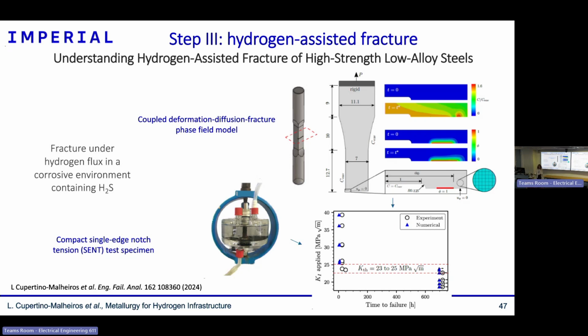Yeah. Sure. Some questions online. Someone asked, how much time does it take for hydrogen desorption to begin in BCC steels after ex-situ hydrogen charging? It depends on your geometry. Basically, you can estimate that. Just take the diffusion coefficient of your material. For a BCC steel it is more or less 10^-10 m²/s. Then you take your geometry, and if you put it in a hydrogen environment for enough time, you can consider a situation where you start fully saturated. Then you just need to solve Fick's law with the boundary conditions that apply. So it would depend a lot on your samples.